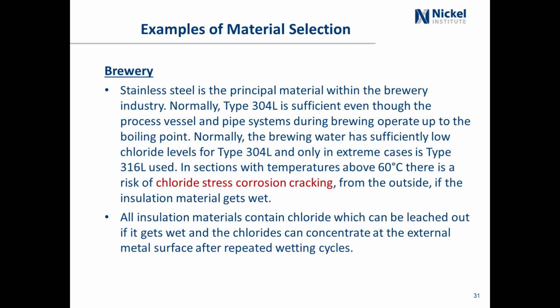In the brewery industry, stainless steel is the primary material. Normally type 304 is sufficient, even though the process vessels and the piping systems are operated at up to the boiling point. And normally brewing water is sufficiently low in chlorides that 304 should not have a problem. I had said before that you could have up to about 200 parts per million of chloride in 304. In typical drinking water, at least here in North America, a lot of places, it's only like 20 parts per million. So if you're using that to brew your beer, there shouldn't be a problem.